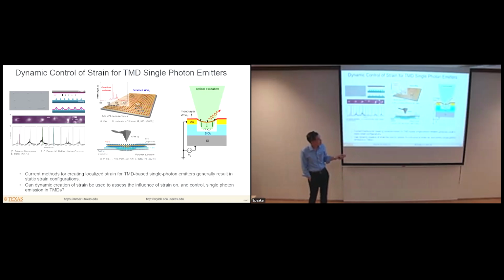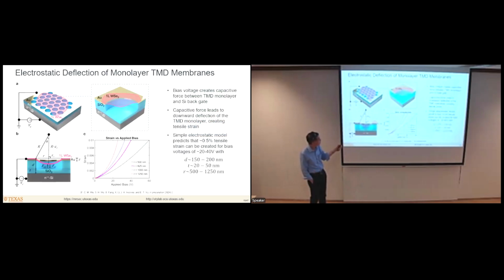And what happens then is that when we apply a voltage between the tungsten diselenide and the silicon backgate, there's a capacitive electrostatic interaction between the monolayer and the backgate. It leads to electrostatic attraction so that this monolayer is deflected downwards and you get tensile strain from this behavior. So this just shows a three-dimensional view of the same thing.